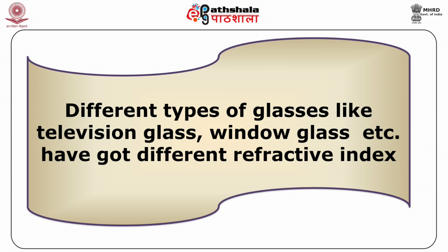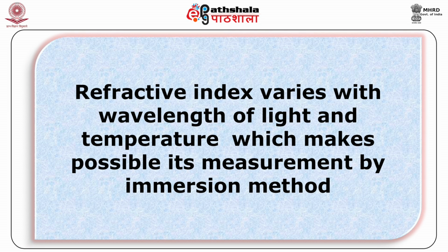Different types of glasses like television glass 1.49, window glass 1.51, etc. have got different refractive index which makes possible their identification. The refractive index varies with the wavelength of light and also with temperature, which makes possible its measurement by the immersion method.